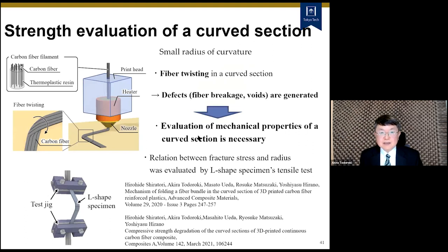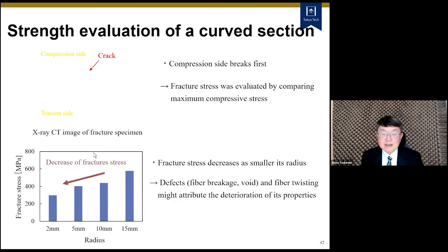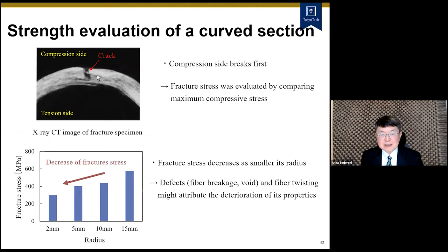And we did another one, strength evaluation of the curved sections. In the curved area, the fiber twist occurred. So we observed the fiber breakage I already showed, and the void. So the evaluation of mechanical properties of the curved section is necessary. So we proposed an L configuration type, L-shaped specimen like this. And we did the tensile tests, but even in the tensile test, the bending moment is applied in this specimen. So actually, this specimen was broken by the compression load. The compression side broke first.